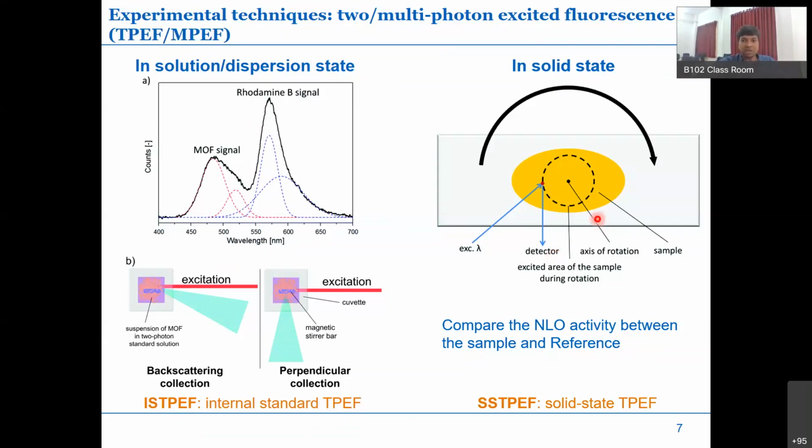So during this measurement also, we usually pack the compound and then start rotating the sample. Why? Because you are exposing your compound to the laser, of course, and specifically very high energy lasers. There may be a chance, not necessarily always, that your compound may decompose if you keep on exposing it. Once you keep rotating it, the possibility of decomposition is reduced, and you also get normalized information. So this is a typical setup we work with.